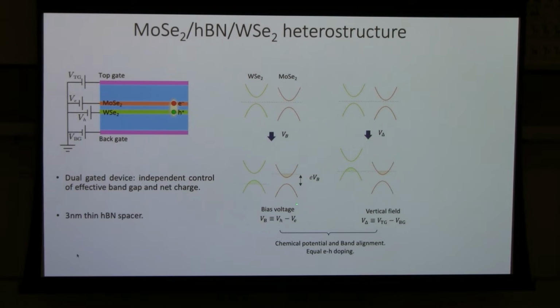In reality, we tend to use both knobs, because if you use only one of them, very often you exceed the breakdown electric field of hBN. So you need to use both effects together, and that allows us to finally reach the electron and hole doping. The other knob we have is the symmetric gate voltage. If we apply the same positive voltage at the top and bottom gate, it will attract electrons, creating a net electron doping. And if you use negative gate voltage, you can create a net positive doping. So these gate voltages allow us to tune the ratio of the electron and hole density. With these two together, we can control the electron density and the hole density separately.